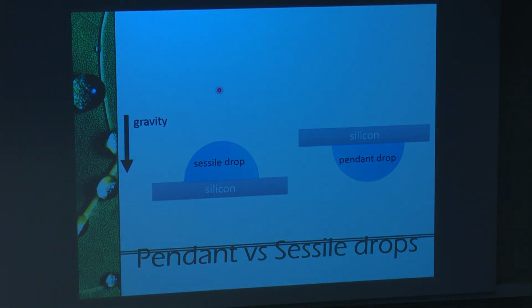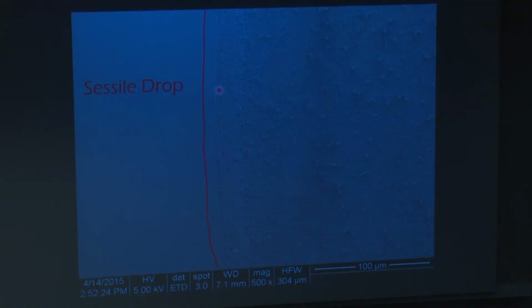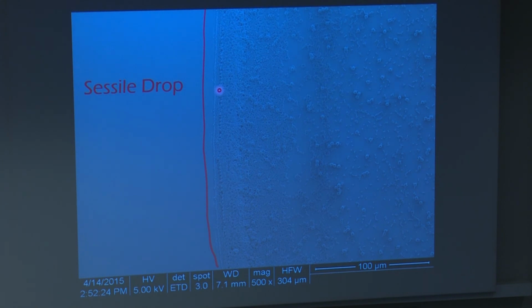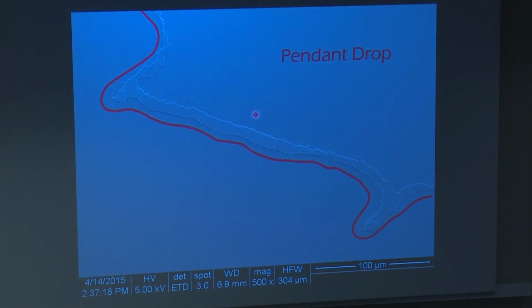So we did this, and then I asked the question, so what happens if we have a sessile drop versus a pendant drop? Well, when we did it with the sessile drop, we got this nice accumulation of the small particles near the contact line, but then you get some big particles, small particles around here, and this is near the contact line. If you look at the pendant drop, number one, the contact line on a macro scale looks like it's fixed, but in the micro, okay. So in the micro scale, you get this pendant drop.